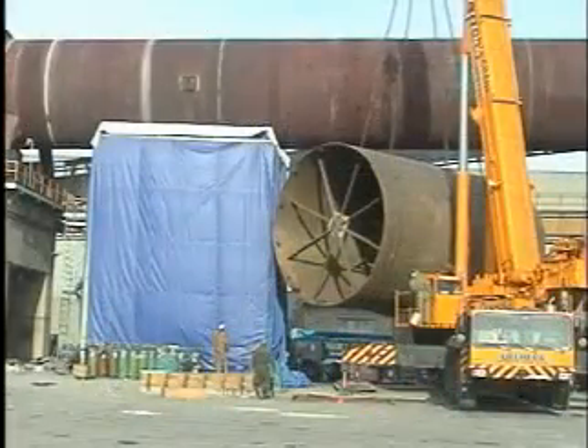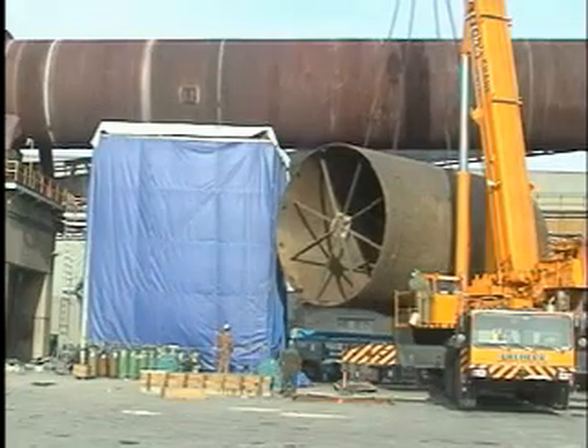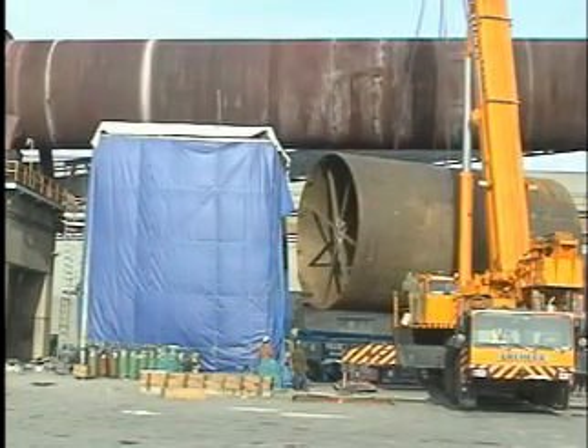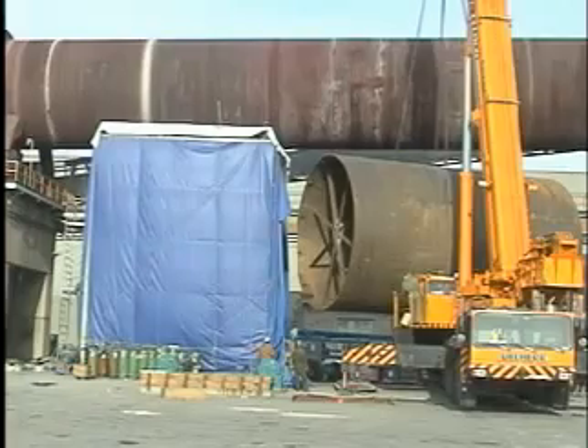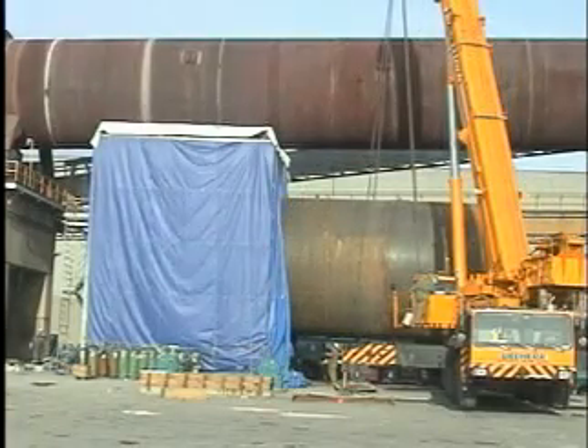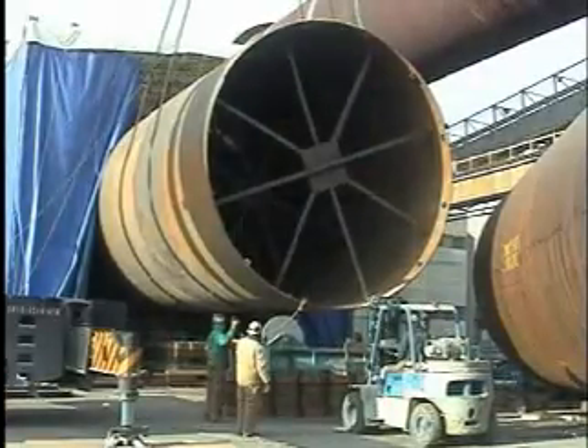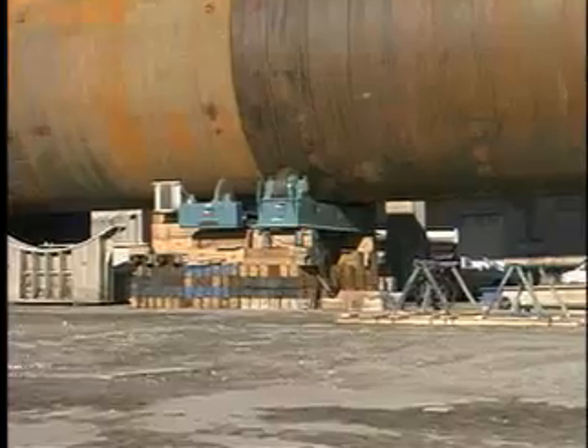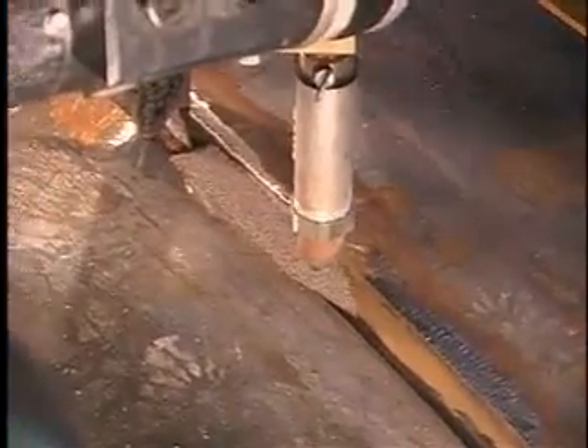Cranes were again used to place the remaining 3 intermediate kiln shell sections. Once the one-piece kiln was assembled to within acceptable dimension tolerances, the shell joint welding was allowed to proceed. The power turn rolls located at the tire support points provided controlled turning of the complete assembly to less than 25 inches per minute, crucial for a quality, automated, submerged arc welding process.